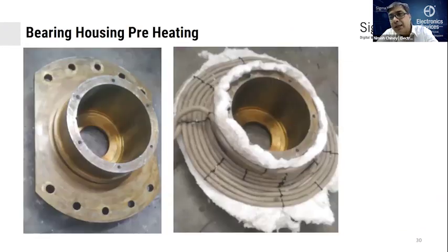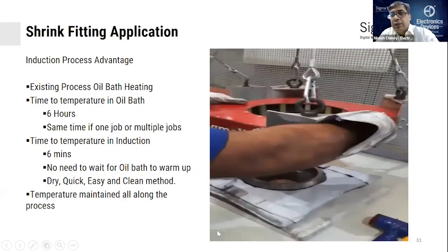Another interesting application is bearing housing shrink fitting. Typically, they put the bearing into an oil bath and let it wait there for 6 hours so the temperature is stabilized. Then they have to remove the bearing housing from the oil bath and insert a bearing. So it's a 6-hour process and it's very messy. The operator has to be very skillful and careful because if he doesn't insert it in due time, the bearing will get stuck. You can see here doing the same with induction.